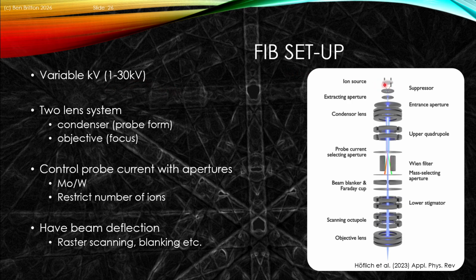We then effectively have this in the liquid metal source. We have the ion source, the suppressor and extractor that enables us to control the ion beam off the tip. We have a divergent probe at this point, and then we go in through an entrance aperture and we condense the probe to go through the system. We have a few details that are important. The Wien filter can select particular energies, so we can monochromate and control the particular ions that are going down the column. And then we can go through the system and then effectively have stigmators and scanning octopoles and an objective lens to bring this to our sample.